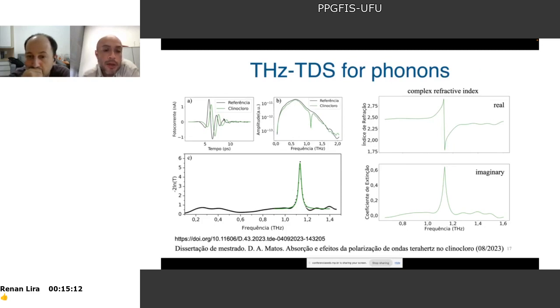And when you have the sample, you can see that it almost doesn't change, but there is a frequency that is absorbed here. There is a very sharp dip, more or less at 1.1 terahertz. And if you then divide the electric field through the sample and through the reference, you can calculate something called transmittance. And from transmittance, here T, you can then calculate absorbance. And here you can see that there is a very nice peak corresponding to a phonon in this material.